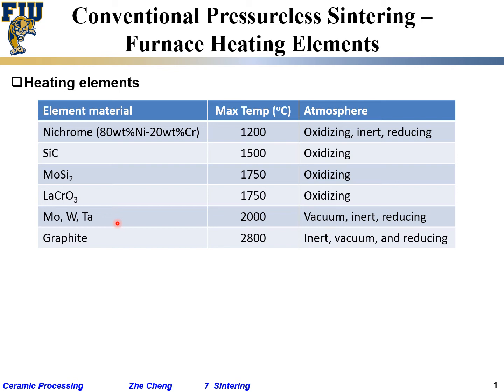Refractory metals such as molybdenum, tungsten, and tantalum have very high melting temperatures and can be used as heating elements, but only in vacuum, inert atmosphere, or sometimes reducing atmosphere. If you expose these to open air, they will oxidize. Unlike the ceramic elements, these allow higher temperatures but cannot be exposed to air, which makes furnaces based on them more complicated to construct — you have to seal them, pull vacuum, provide gas, and ensure no leaks.